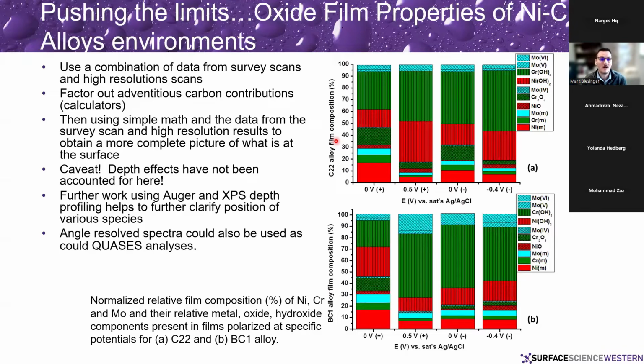We've done that here for some C22 alloy, which has some thin film oxides on the surface, and it's been broken down. We've got so much of the metals present, so nickel metal, chromium metal, molybdenum metal, and then the various oxides that are present as we change what we've done to this system, and for a variety of different electrochemistry that has been done on these systems. And so that's one way to look at these things, and you break down and say, oh, okay, we really have a lot of chromium hydroxide versus chromium oxide, so it's dominated by hydroxides, or dominated by oxides, depending on what chemistry's been done.